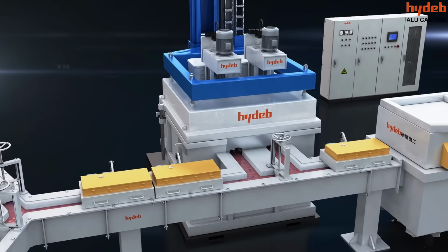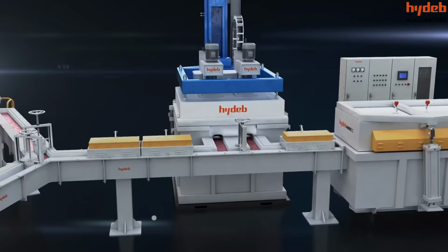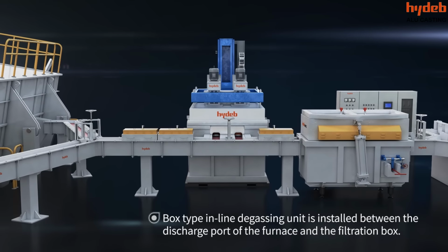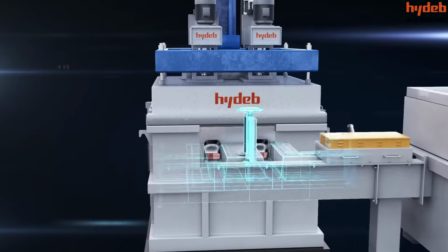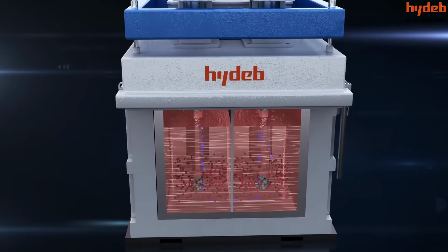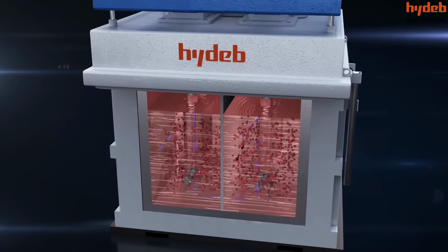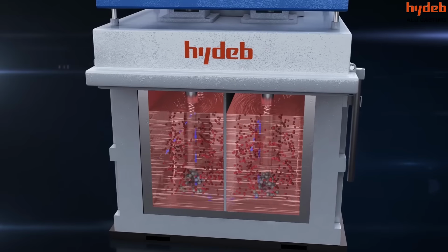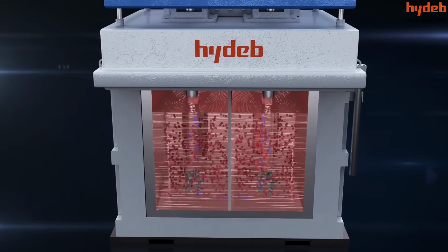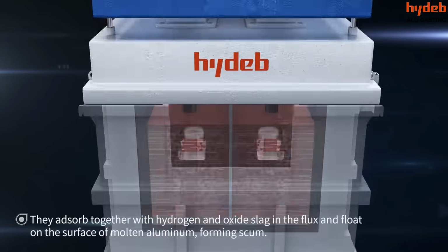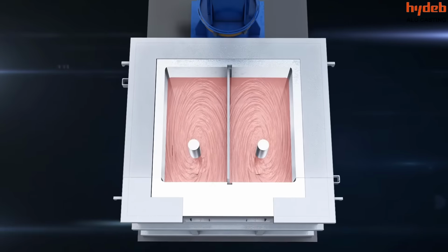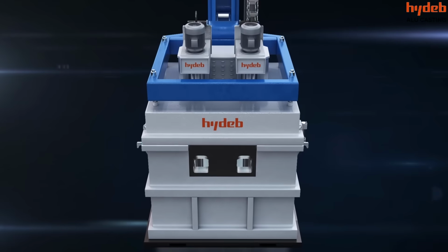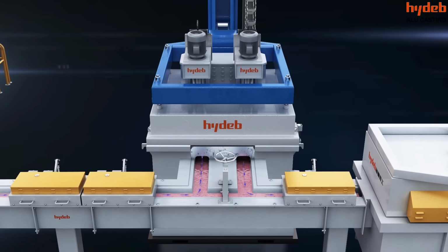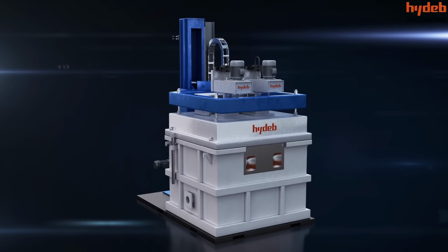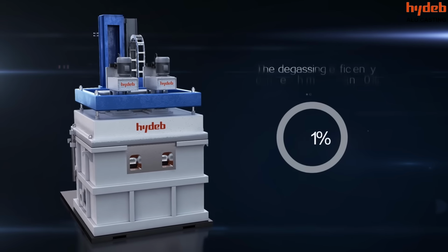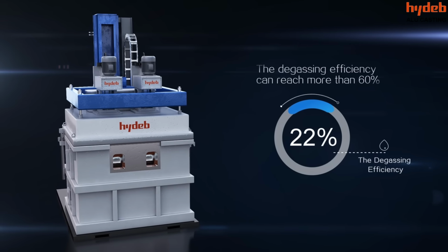Box-type inline degassing unit is installed between the melting furnace and the filtration box. Under the action of a rotating rotor, inert gas forms a large number of dispersed bubbles and enters the molten aluminum. They adsorb together with hydrogen and oxide slag in the flux and float on the surface of molten aluminum, forming scum. The molten aluminum flows out from the outlet of degassing unit, thus achieving the purpose of continuous inline refining. The degassing efficiency of box-type inline degassing unit can reach more than 60%.